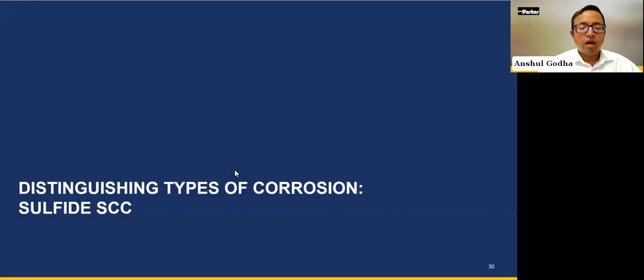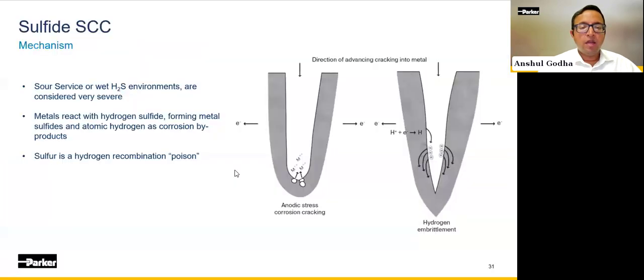Next, let's talk about another common form of stress corrosion cracking, which is sulfide stress corrosion cracking. In terms of mechanism, it is very similar to hydrogen embrittlement in the sense that it is also caused by hydrogen atoms diffusing into the metal and forming hydrogen molecules, thereby causing the stresses. However, the one big difference here is that there is hydrogen sulfide present in the environment.